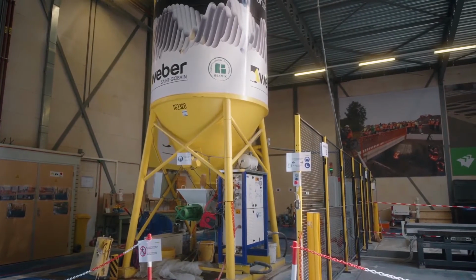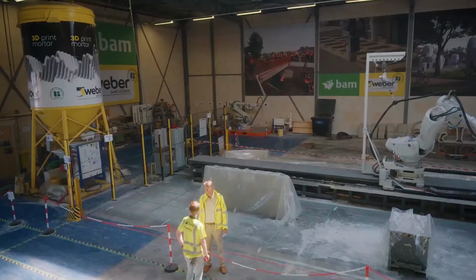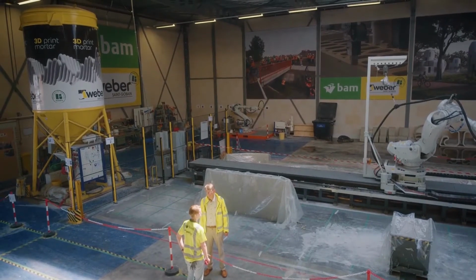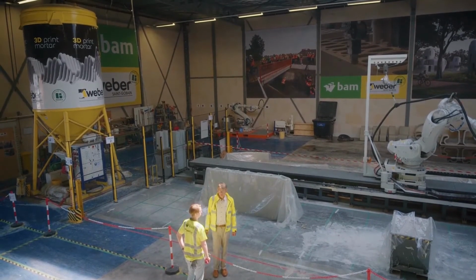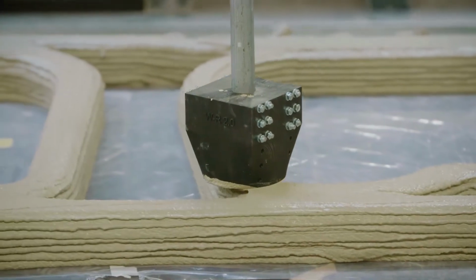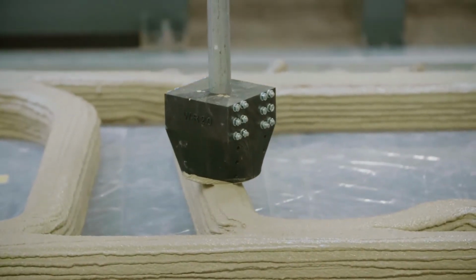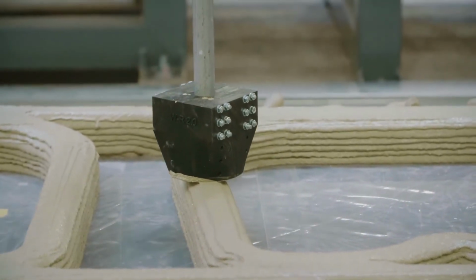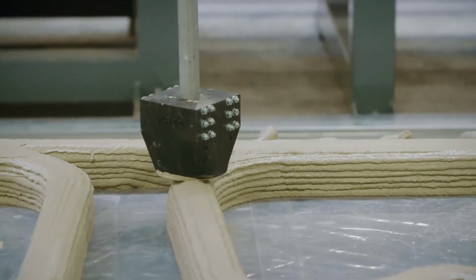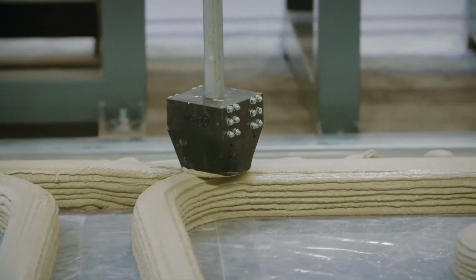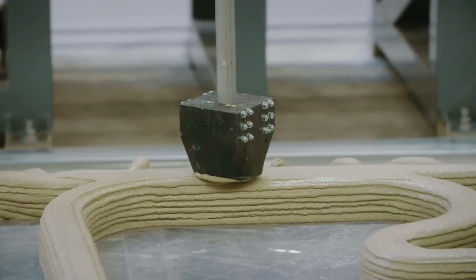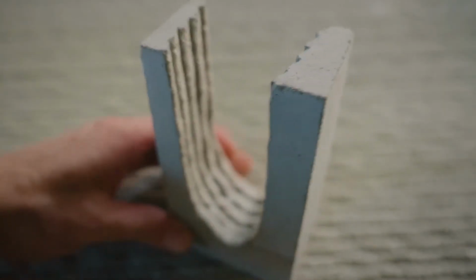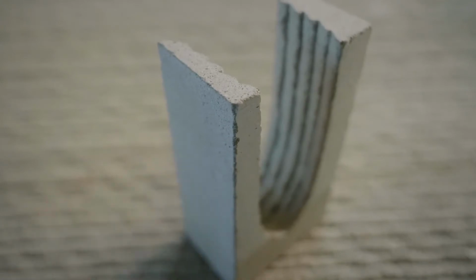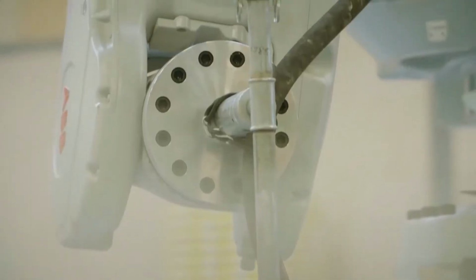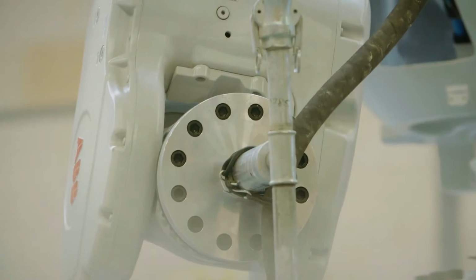But another benefit of having an OPC mortar is that the rules that apply to concrete, you can extrapolate this to this mortar because a lot of things are known about ordinary concrete. Another thing is when you have a mortar that doesn't harden immediately but that has an open time of about 90 minutes, it's much easier to get a monolithic structure. That means that the quality of the layer of the interface, that's the layer between the layers, has the same performance as the bulk of the material.